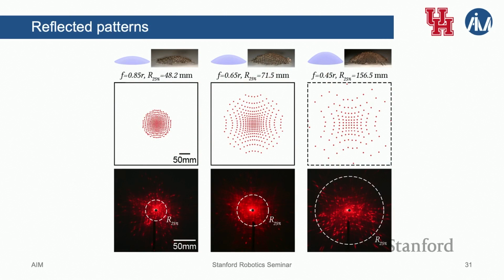From geometrical optics, we can predict exactly what the pattern should be of the actual deployed structure. And so depending on the focal length, you can see some patterns diverge a lot less than some other patterns. So this one diverged way beyond the imaging plane, so we can collect all the reflected lights. And we can see from the experimental photographs, they pretty much reflect what we predicted them to be.